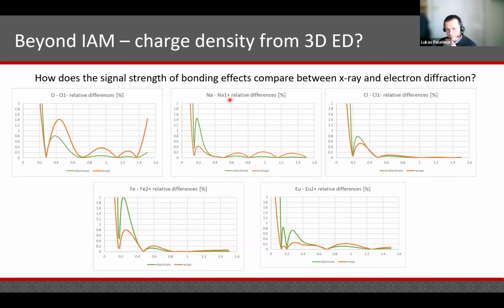And the green curves show the difference in scattering power for electrons, and the orange curves for X-rays. And you can see that, on the horizontal axis, there is a diffraction angle or length of scattering vector in reciprocal angstroms. So at very low scattering angles, electrons are always better than X-rays. You see that the green curve is above the orange one.